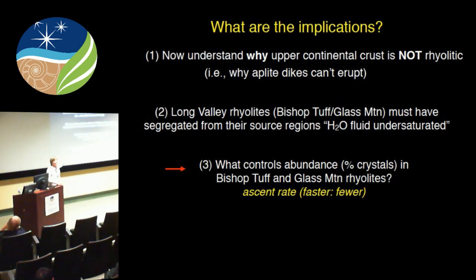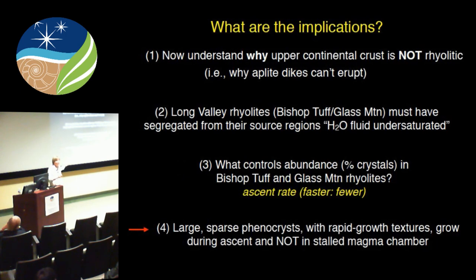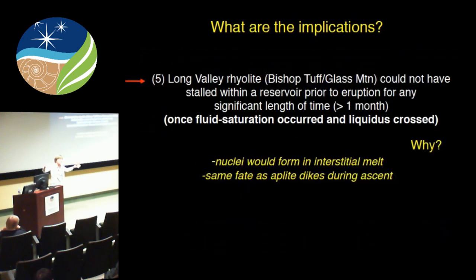The other thing, and this is what is kind of radical, is that these large sparse phenocrysts are not growing in a magma chamber stalled at depth over long periods of time, but they're growing during transit to the surface. And if that's all true, then the Long Valley rhyolite could not have stalled. That 10 by 20, 3 kilometer melt body couldn't have been sitting there. I don't see how it could have been stalled for even a month.